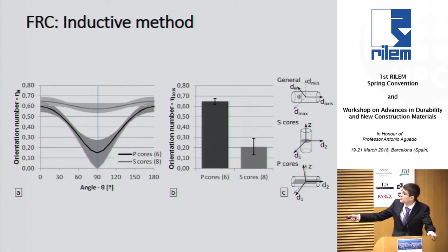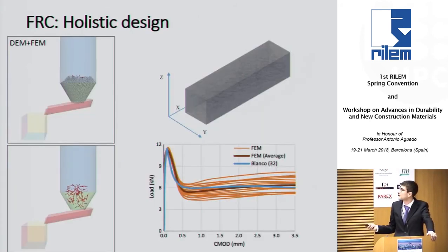And what you see here is the orientation number measured with the equipment. So different angles, so let's say we are spinning the specimen that we are measuring and measuring how much fiber is aligned with each angle. And you see that in sprayed concrete, for instance, you have a very high anisotropy. So you have a certain direction with a lot of fiber aligned with it, but there's a direction that has a very small number of fibers aligned with this. And this was what we observed because fibers, when we spray, tend to align parallel to the surface. It's reasonable. The fibers are getting there, impacting the surface, and spinning, getting parallel to the surface. So the test allowed us to do this type of prediction, to understand what is happening. And the test is now used in many labs in the Americas, also here in Europe, and in some real projects already, for the control of fiber content and orientation.